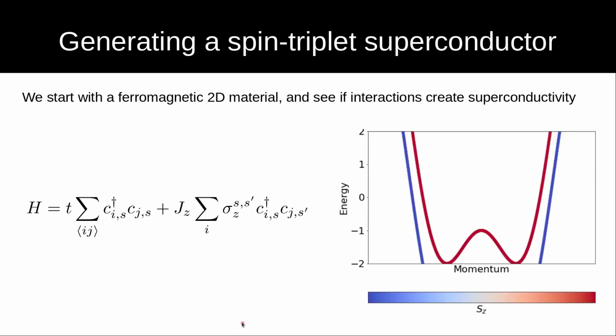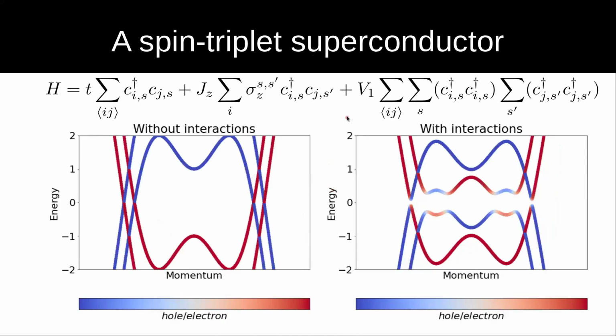And this is something that is relatively easy to do with a toy model. So you start with your Hamiltonian for a ferromagnetic system where you introduce your exchange field by a term like this. And then afterwards, you introduce your attractive interactions. And you can now solve this at the mean field level. And when you solve this at the mean field level, what you actually observe is that a gap opens up between the electron and the hole sector, which is this gap that you see over here. So now you have a superconducting state, but at the same time, you have a system that is magnetic because of this term. So this type of self-consistency effectively gives rise to a spin triplet superconductor.